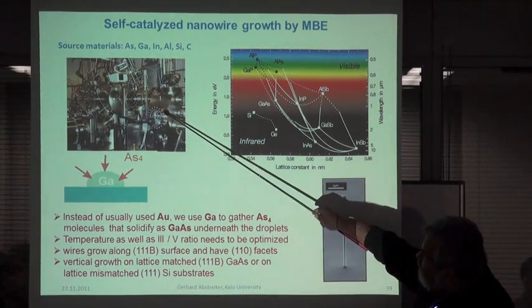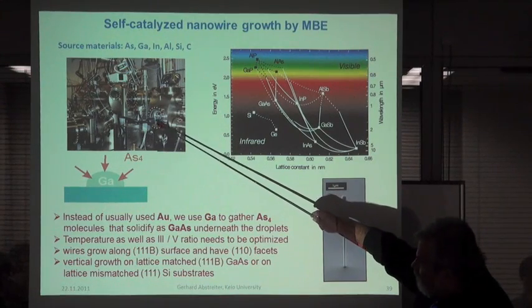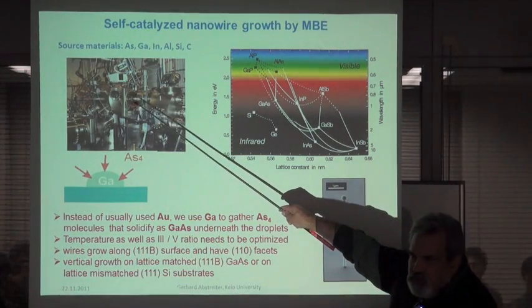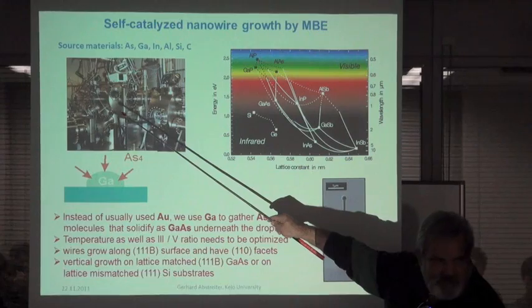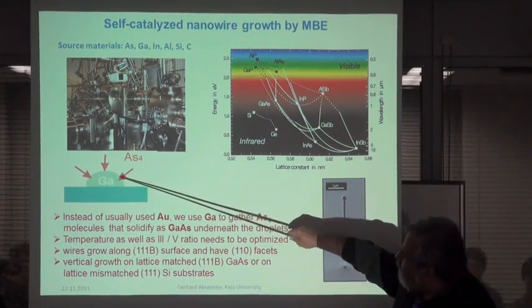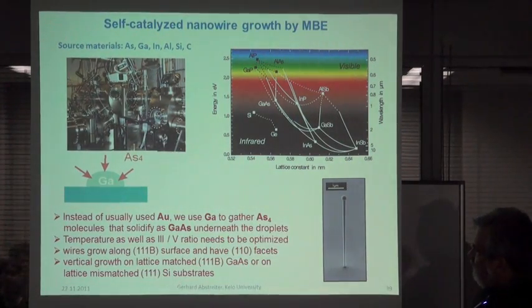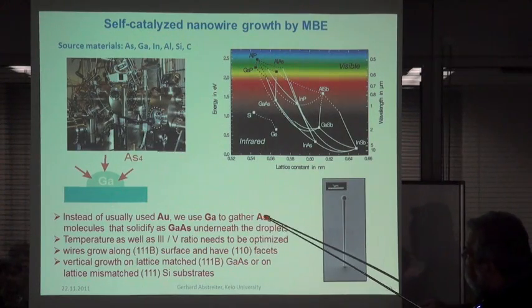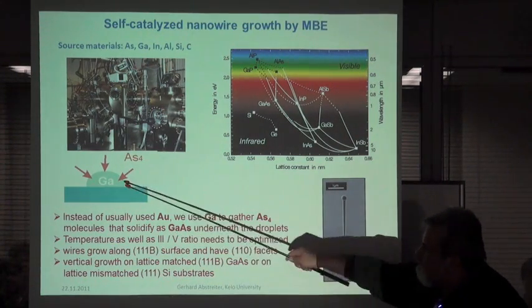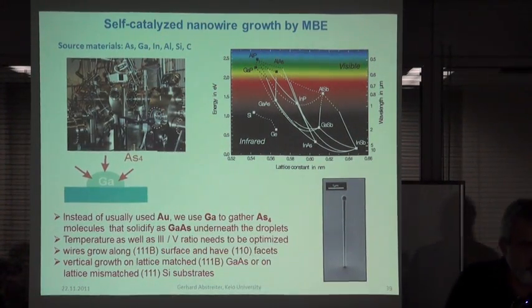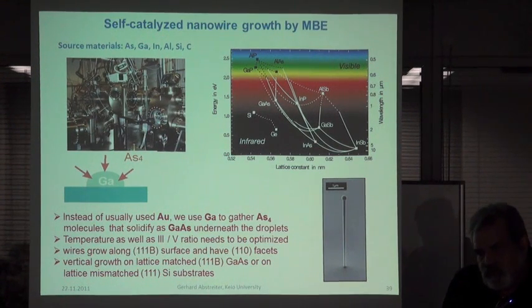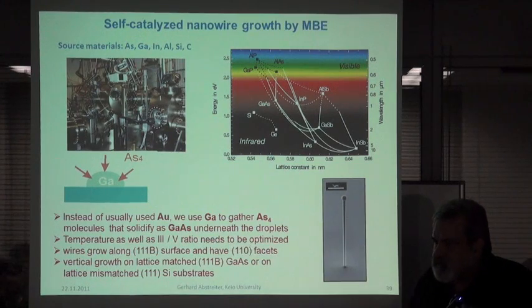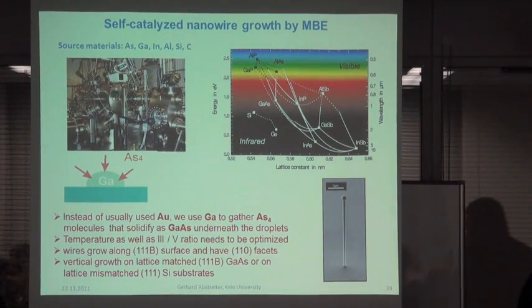And so we said I don't want to have gold in this machine because it's an ultra high purity MBE machine where we have very high mobility. So can we do this with gallium, for example? So instead of gold, we use gallium, and then we gather arsenic 4, but then we use this droplet also for growth. Gold would just be lifted upwards. The gallium is used as a material for growing the gallium arsenide, so we have to open also the gallium shutter and provide enough gallium to have it stable.